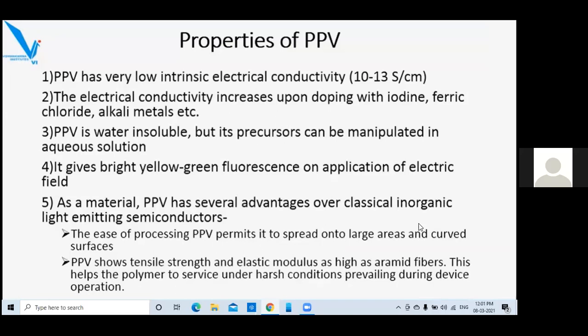PPV is water insoluble, but its precursor can be manipulated in aqueous solution, so that becomes easy to apply. It gives a bright yellow-green fluorescence on application of electric field. As a material, PPV has several advantages over classic inorganic light emitting semiconductors. Number one, the ease of processing of PPV permits its spread onto large area and curved surface. PPV shows tensile strength and elastic modulus as high as aramid fibers. This helps the polymer to survive under harsh conditions prevailing during the device operation.